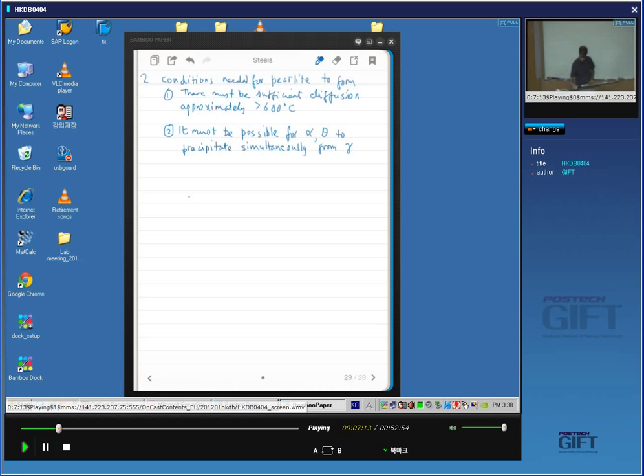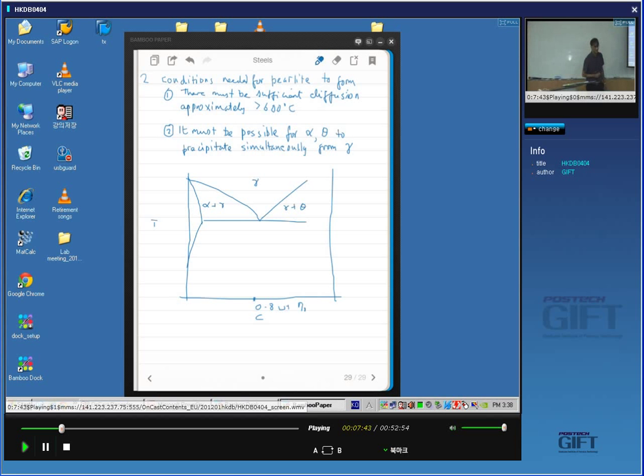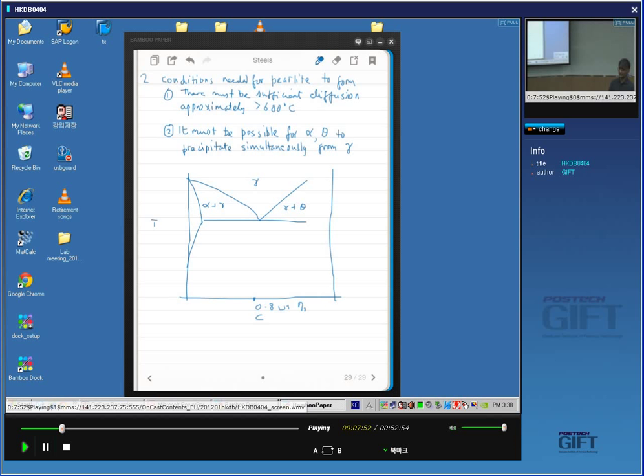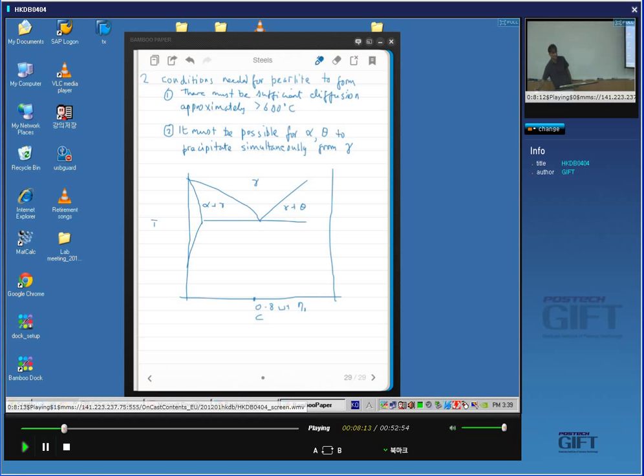Let's go into the theory of the pearlite transformation. What is the condition which ensures that you can precipitate both cementite and ferrite from austenite? On the iron-carbon phase diagram, we have austenite, a ferrite-plus-austenite region, and an austenite-plus-cementite region, with the eutectoid concentration at about 0.8 weight percent. The concentration has to be at this eutectoid point, where all three phases can co-exist in equilibrium at approximately 723 degrees centigrade.